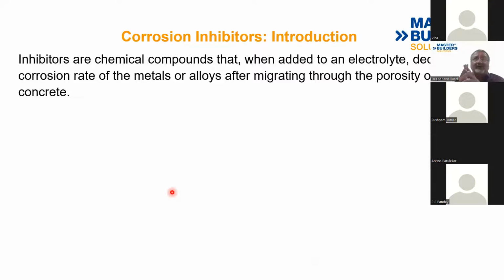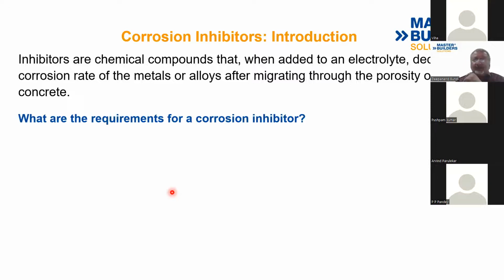We all know that concrete is a porous material. Yeah, it has a good amount of pores, and through these pores, if I allow these inhibitors to pass, because they have very high vapor pressure, they will penetrate inside the concrete, and they have affinity towards steel, so they will move towards them. So what are the requirements of a corrosion inhibitor we are talking about? We are talking about these corrosion inhibitors when you apply on the surface of the concrete, either after the repairs or on a new construction, right?